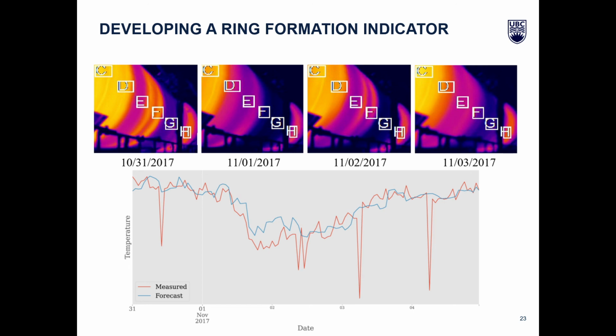The bottom figure shows the measured and forecasted kiln shell temperature during these days. The consistent mismatch between the forecast and the measurement, particularly around the beginning of November 2nd, explains the daily indicator count for ring growth.